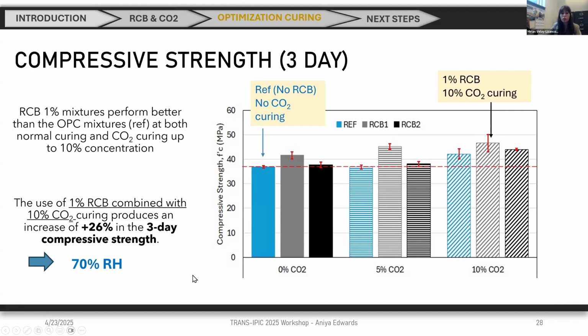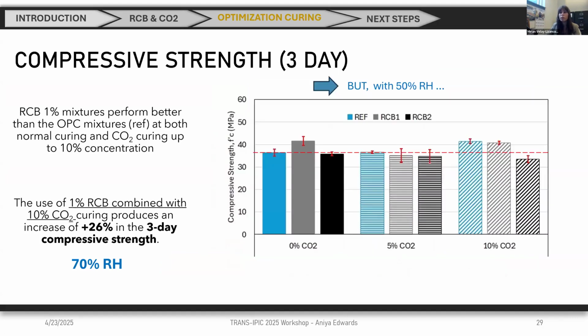Now, if we show you the results with 50% relative humidity, you will see that they are different. Still, carbon black performs better with no CO2 curing, but with 1% there is not much of a difference, and with 10% CO2 curing, the reference is the same, or even slightly outperforms, I would say it's the same as with recovered carbon black. So this is just showing you how the relative humidity during the curing process, during just the few hours that we do CO2 curing or not, changes a lot the combined effect of CO2 curing and recovered carbon black. That's why it's so important to complete this matrix to finalize the model and see what the best conditions are.